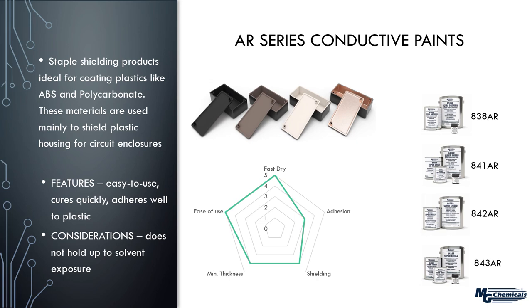Now these are great products in that they're easy to use, they cure relatively quickly, and in terms of plastic adhesion, they perform very well. But there's other things to consider that would make them less ideal. For example, they may not necessarily adhere well to metallic or, say, concrete substrates. So that's something we need to consider, as well as the environment. In particular, any kind of solvent exposure, whether it's fuel vapors, things like that, it's not really going to hold up in the long term. So something to consider when you look at acrylic resin as a possible solution.